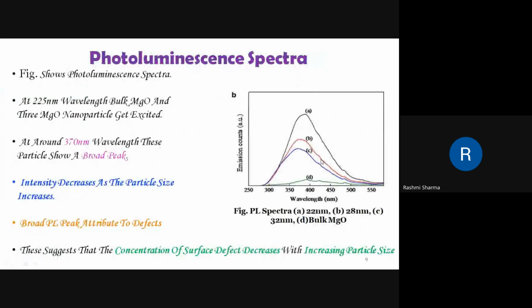This is the photoluminescence spectra for different size nanomaterials and for bulk. A is for the smallest size nanoparticle, which is 22 nanometer, B is for 28 nanometer, C is for 32 nanometer, and D is for bulk. In this curve, around 370 nanometer, these particles show a broad peak. As the particle size is increasing, the intensity of the peak is decreasing.